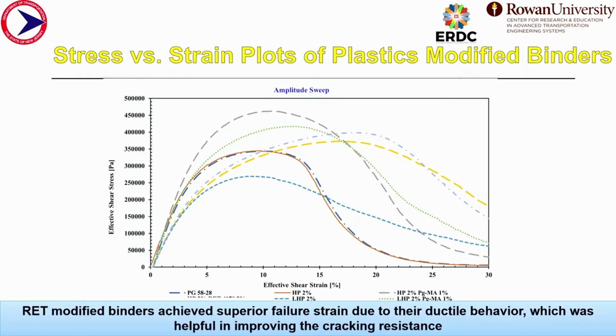So from here, we can again see that the RET modified binders, both for the HP and LHP, especially for the LHP, are performing better and showing ductile behavior, which was helpful in improving the cracking resistance that we have seen already in our previous slide. So what can we conclude from these results?